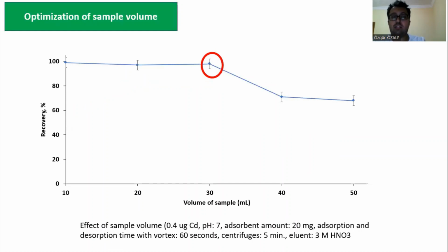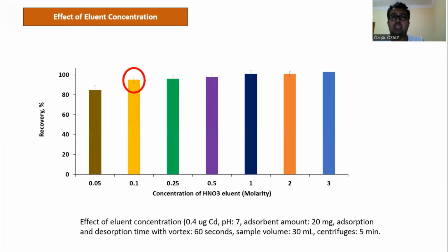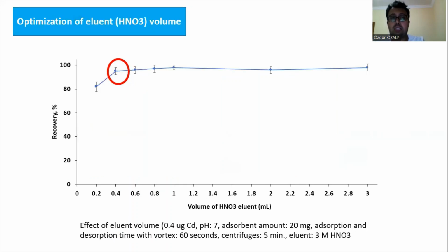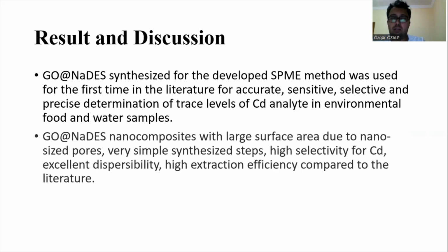Optimization of sample volume is very important for the pre-concentration factor. We select 30 milliliters. For eluent concentration, we tested different nitric acid concentrations and select 0.1 molar. Last is the eluent volume, where we select 0.4 milliliter. For pre-concentration, we calculate 30 divided by 0.4, which equals 75.